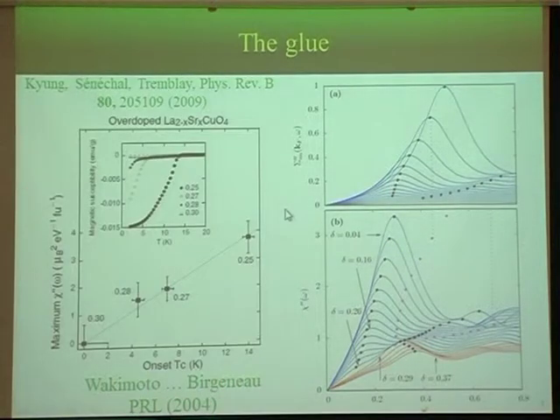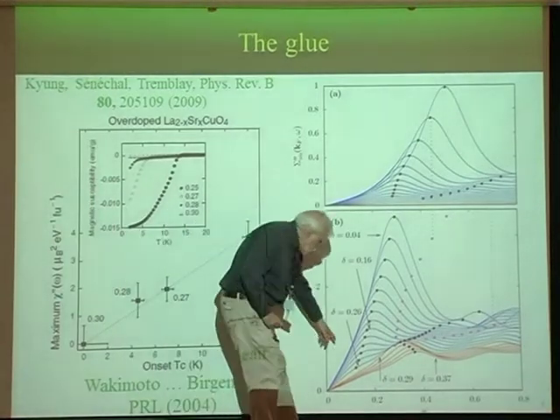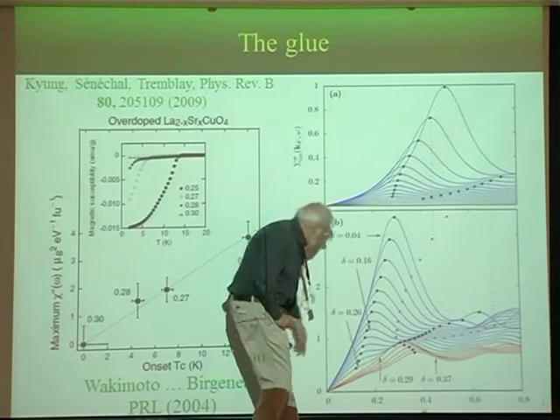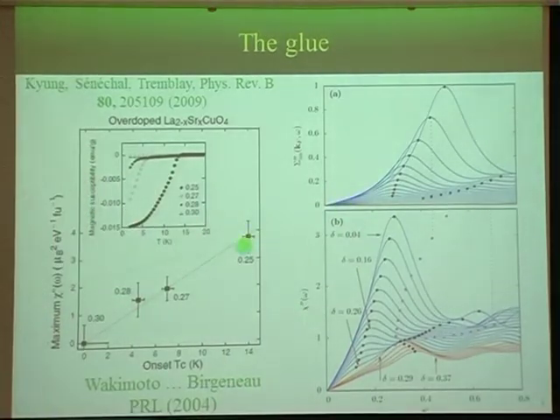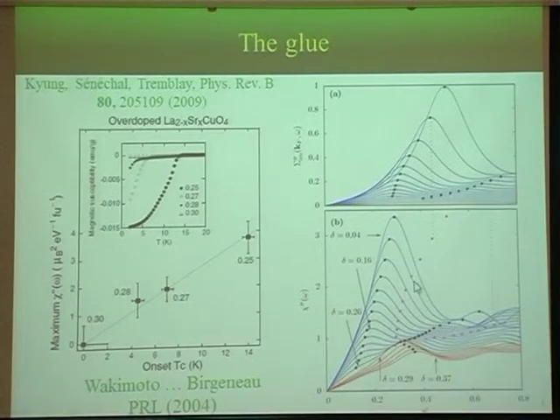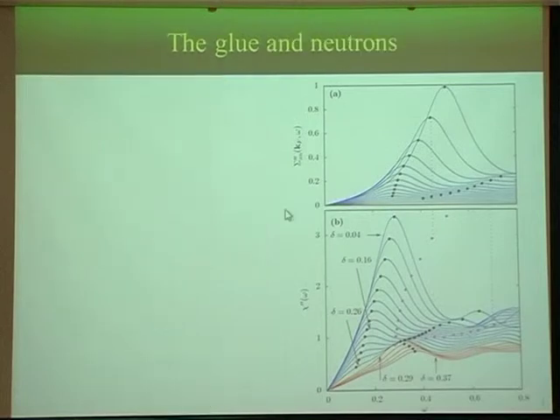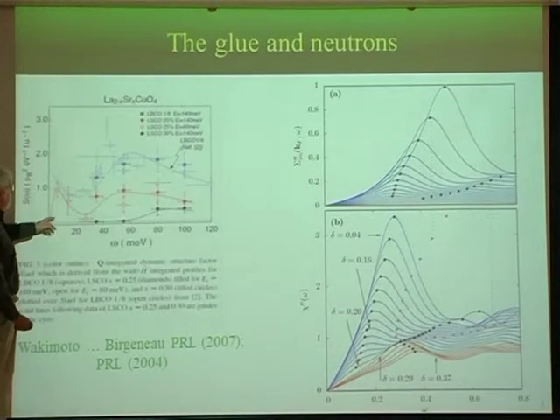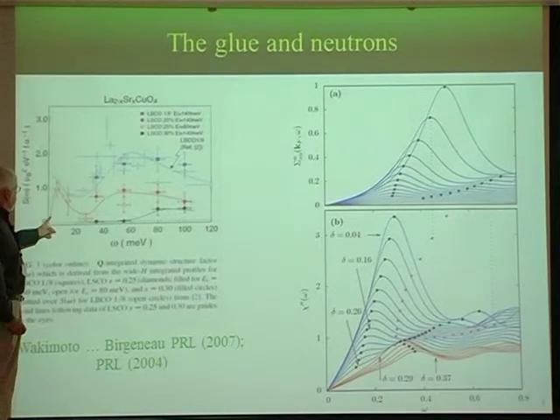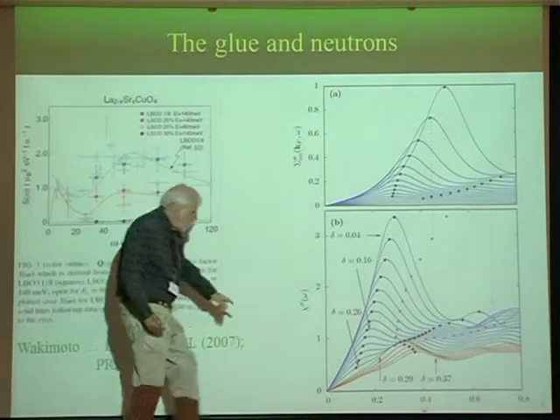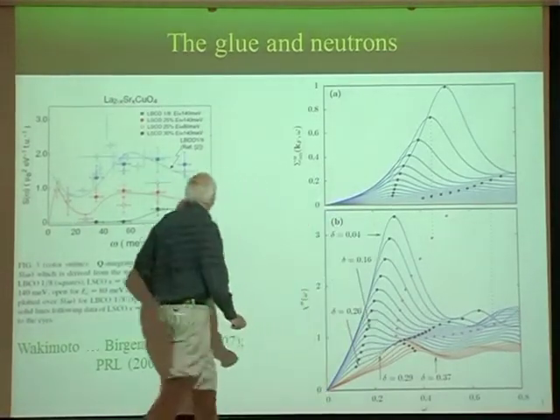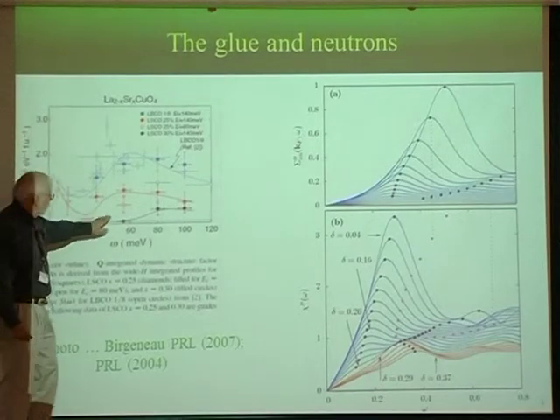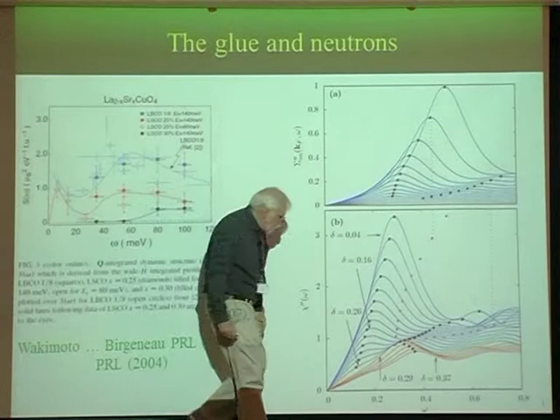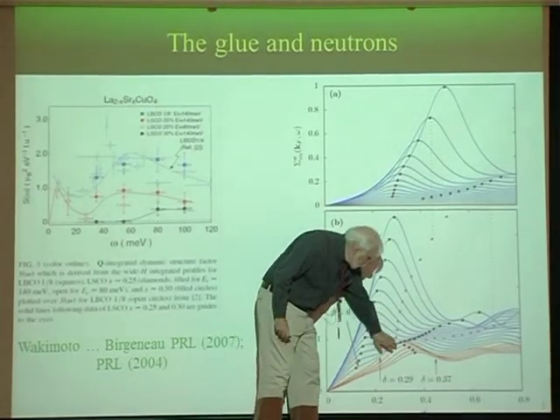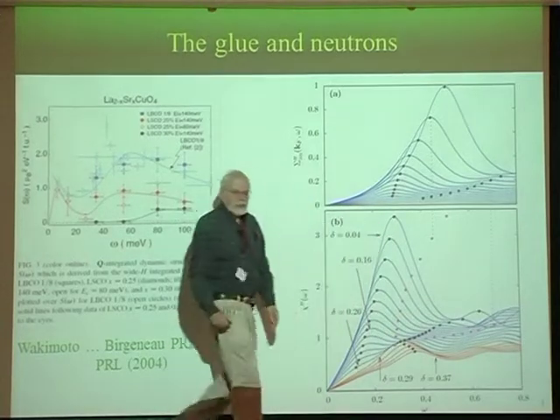If you look at experiment, there are experiments by the group of Birgeneau that looked at the size of this low frequency bump here. What they see is that it goes to 0 at the same time as Tc on the overdoped side goes to 0, which is consistent with this. And if you look at the shape of the spectrum of this chi double prime measured experimentally, you see this two-bump structure in this general area. If you go to the normal state, you see that the low-frequency peak disappears, and this shifts to the right. The red curves here are in the normal state. So you see that the low-frequency bump has disappeared, and it has shifted to the right. All these qualitative aspects are there.